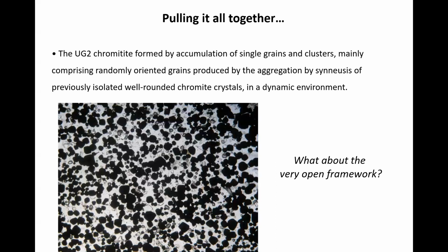But the final thing that people are going to jump down my throat on is to say, what? This is a really open framework, right? If you have single grains of chromite and you drop them into a beaker, your porosity is going to be about 30%, give or take, depending on what your grain size variation is, because your small grains will fill in the spaces between the big ones. We've got a really, really open framework.